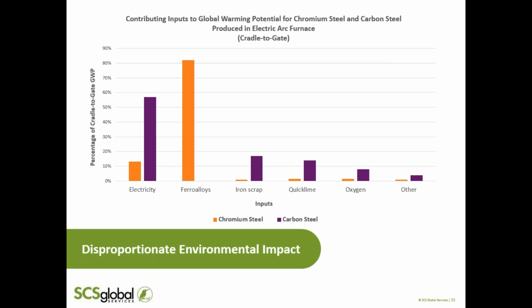The graph here shows the relative global warming potential for two different steel products of the same product group. Chromium steel is shown in orange and carbon steel is shown in purple. Both products are produced in an electric arc furnace, and results are expressed in kilograms of carbon dioxide equivalents per kilogram of product. We can see that for carbon steel, electricity used at the steel mill has the largest contribution to impact. Alternatively, in the case of chromium steel, ferroalloy inputs, which typically make up 15 to 20% of the product by weight, such as ferrochromium, ferronickel, and ferrosilicon, have a substantial contribution, if not the largest, to the cradle-to-gate environmental impact of the product.